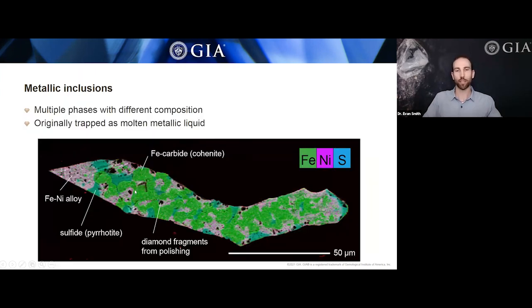So this is a cross section through this inclusion, and the colors correspond to different atoms here, different chemical elements. We've got iron, nickel, and sulfur. And this inclusion has multiple phases within it. So we see three main phases: this bright green phase, which is an iron carbide called cohenite. There's this aqua kind of teal or turquoise phase. It's a sulfide, an iron sulfide called pyrrhotite. And then in purple here, we've got this iron nickel alloy.